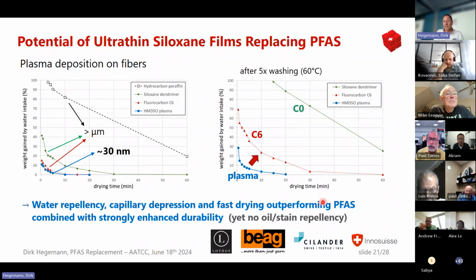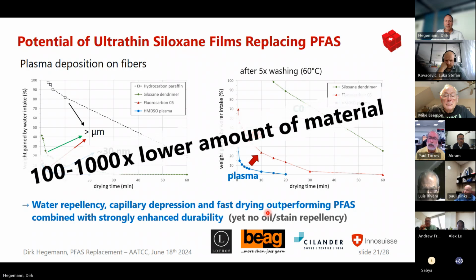However, when it comes to oil stain repellency, this is wetting. So this is a very nice approach, however, only for hydrophobicity. And I'd like to stress this is a nanometer thick coating. So we are using 100 to about 1,000 times lower amount of material than with the wet chemical approach.